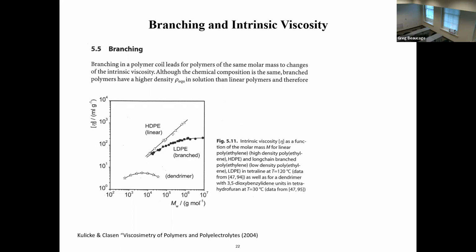But as you add more polymer in concentration, you add in the counter ion also. So you salt out the charge as you go to higher concentration. At that point, it goes from a rod to a coil. Then the intrinsic viscosity drops from a power of 2 to a power of 0.8 in molecular weight. So the whole thing gets messed up with polyelectrolytes. It's a lot more complicated, right? A few people have looked at it, particularly Colby at Penn State, who's looked at it in depth.